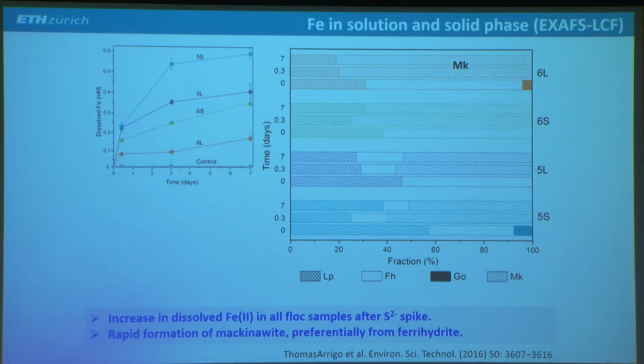So the explanation for this is probably the different ratio between spiked sulfide and total iron in the system. And the reason for this is that, remember, we used a constant solid to liquid ratio, but the floc samples had different iron contents. So the iron content in the floc sample is not constant, so therefore this ratio was not constant. And in the top two samples, we had ratios above 1. So we had the highest ratio here and the lowest ratio here. So we think that this is probably the reason why the transformation was not complete in these cases, because it's just less sulfide compared to total iron.